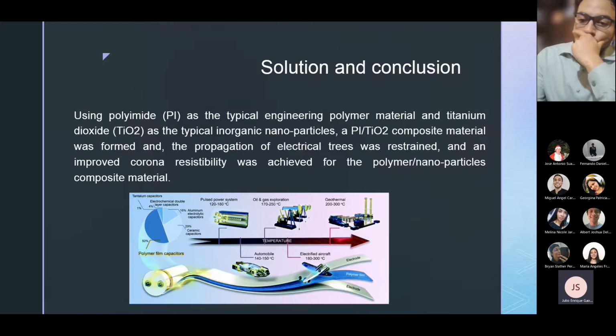The polymer material around the nanoparticles was gradually decomposed in the corona process, leaving the nanoparticles behind in the decomposition channels and on the surface of the composite matrix. The nanoparticles were gradually deposited and the decomposition channel of the electrical tree was eventually blocked by the deposited nanoparticles, shutting off the alternating current in the decomposition channel. That is to say, the propagation of the electrical tree was restrained in the corona process, and improved corona resistivity was achieved for the polyimide and titanium dioxide composite material. The application is electrical aircraft and automotive. Thank you.